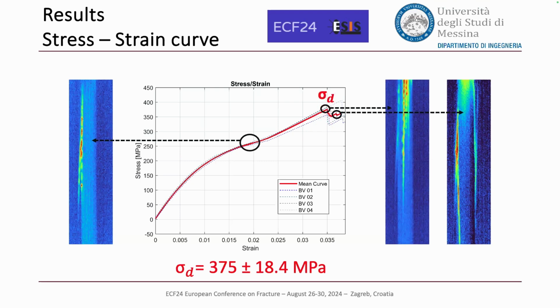Our consideration regards the sigma of delamination, which we consider as the first damage of the specimen, and it is about 375 megapascal.